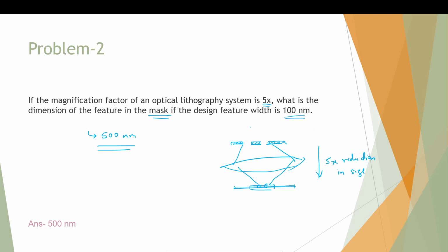So the laser writer will have a resolution that might not be as high as the resolution that we require. So we can have a 500 nanometer resolution at the laser writer stage. However, because we are using projection lithography, we are able to write very small features that are 100 nanometer. So that is the advantage of using photolithography.